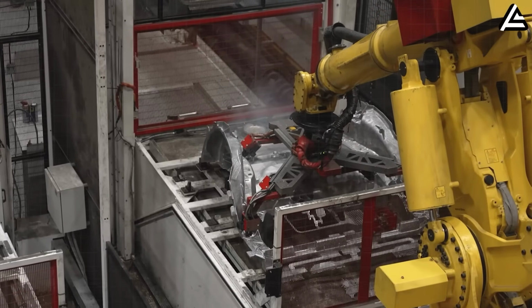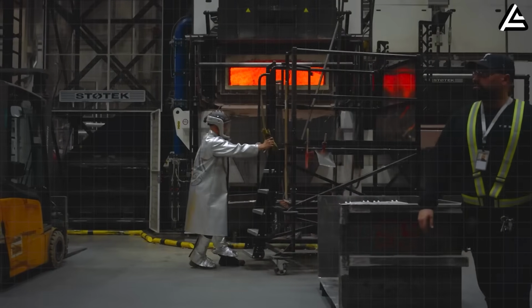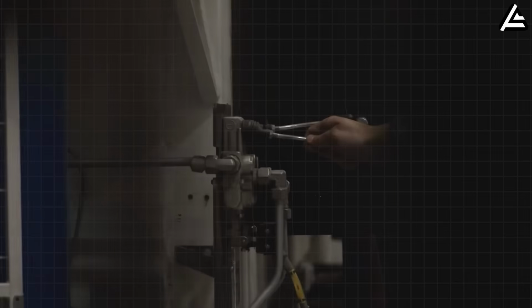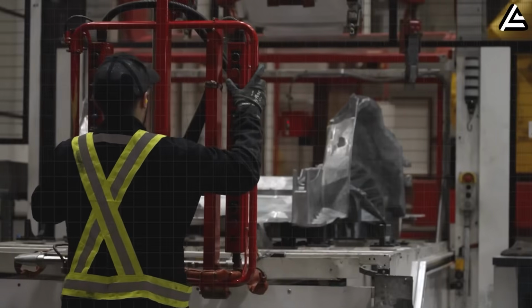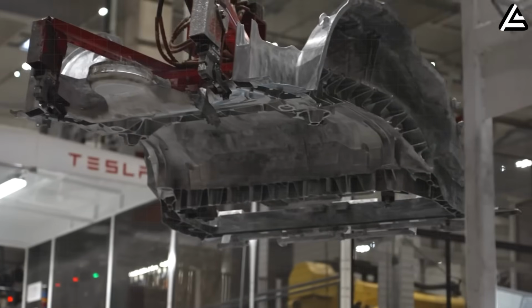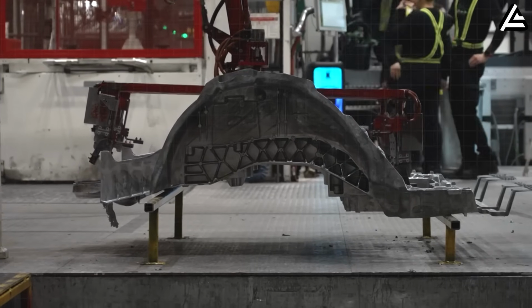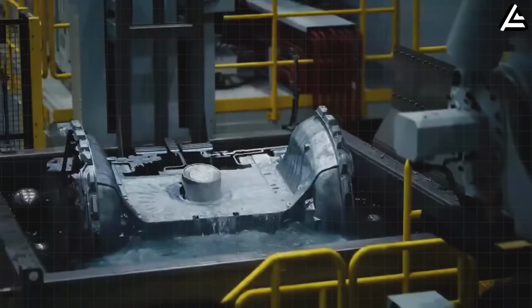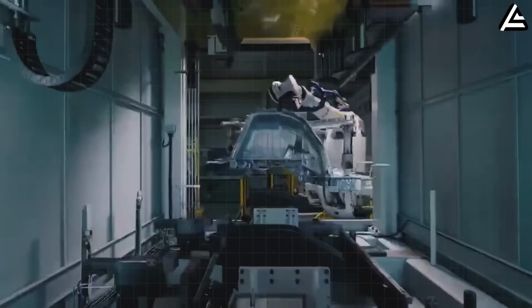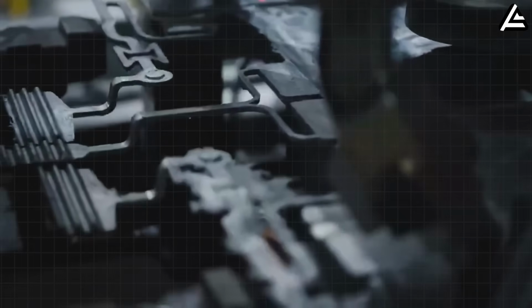Cycle time is insane: 19 seconds to inject, 45 seconds to cool and extract. Then the die opens and the robot grabs the next red-hot piece. That's less than 2 minutes from liquid metal to finished structural component, compared to the 12 to 15 minutes it takes legacy automakers to stamp, weld, and rivet the equivalent assembly.